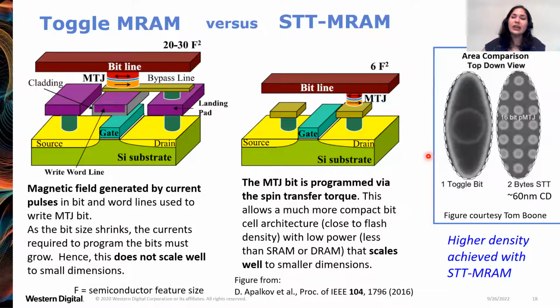In this top-down SEM image on the far right, I'm showing 16 perpendicular magnetic tunnel junction bits. Each one of them is about 60 nanometers in diameter. And 16 of these bits occupy the same area as just one toggle MRAM bit. So it's easy to see here that it's with spin transfer torque MRAM that we will achieve a higher density magnetic-based memory.